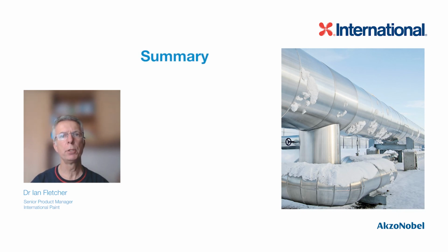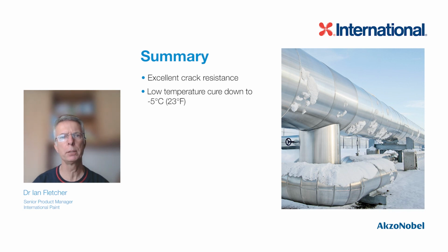So to summarise, Interbond 2340 UPC, a next-generation epoxy phenolic, has been formulated to provide very good corrosion resistance at both ambient temperatures and in the CUI zone, provide excellent crack resistance if over-applied, provide low temperature cure down to -5 degrees Celsius, and have enhanced erosion resistance. Interbond 2340 UPC greatly simplifies specifications, which means faster shop throughput and less waste for fabricators and applicators, less rework costs and project delays for fabricators and EPCs, and greatly reduce CUI risks for owners and operators.